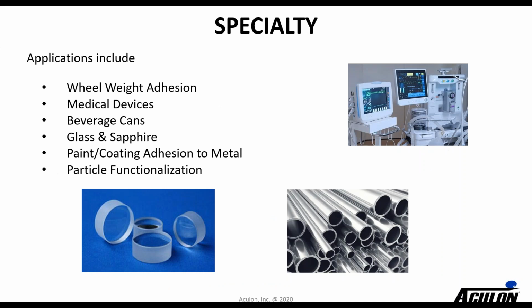So last but not least, we've got our specialty business, which is a broad range of different things, both in the medical areas as well as solving some wheel weight adhesion issues. These are the weights that go on the side of the wheel to balance them out. A lot of times, with temperature and humidity and the new coatings that they want to put on the wheels that provide brake dust repellency, the weights also needed a real boost to stay adhered. We've also got a number of medical applications where you've got dissimilar materials that need bonding. We've had nice success and good results in some packaging, also optics, and a lot of paint and coating adhesion to metal is important. Also particles: there's an interface between a particle and the resin, and being able to modify the particle to react with the resin can be very important.